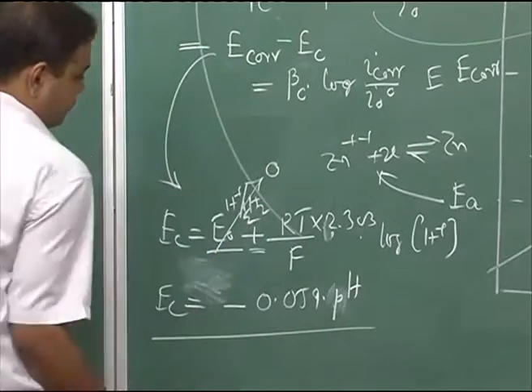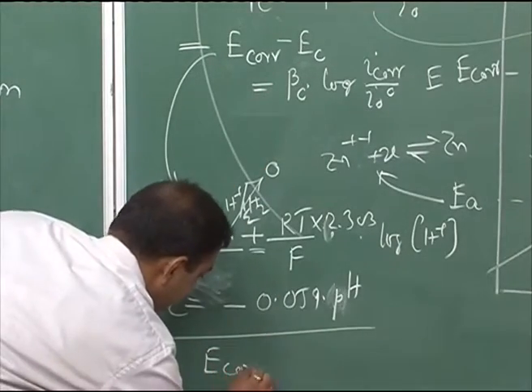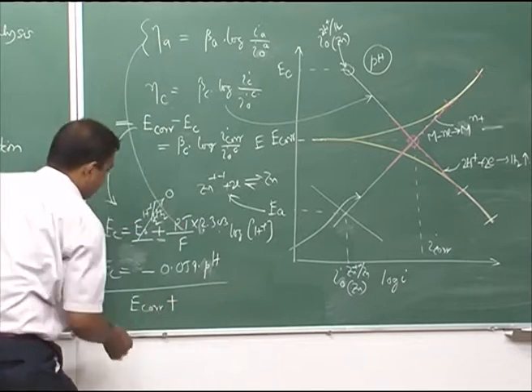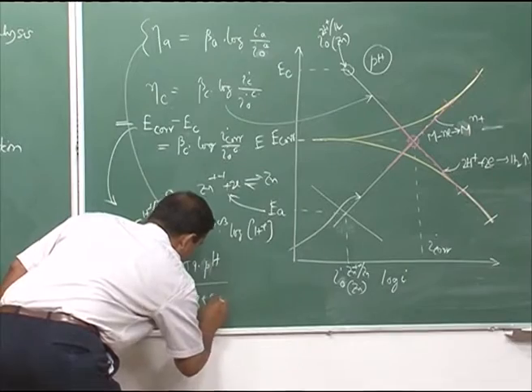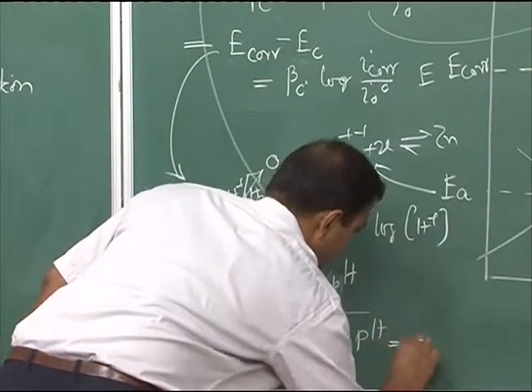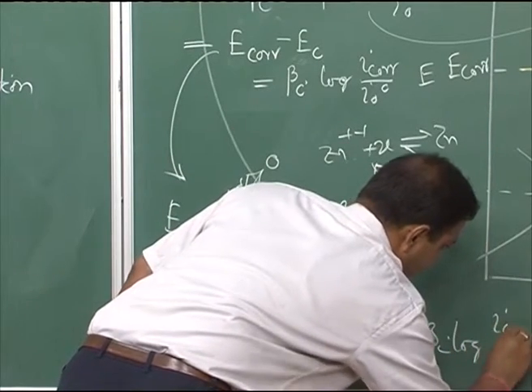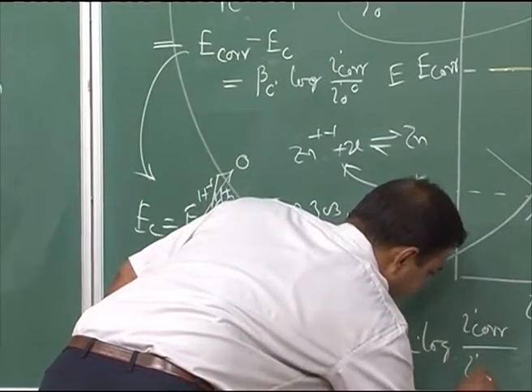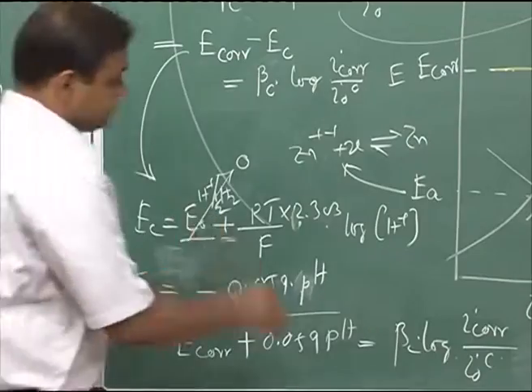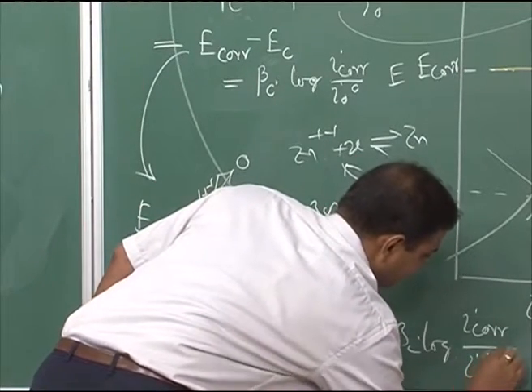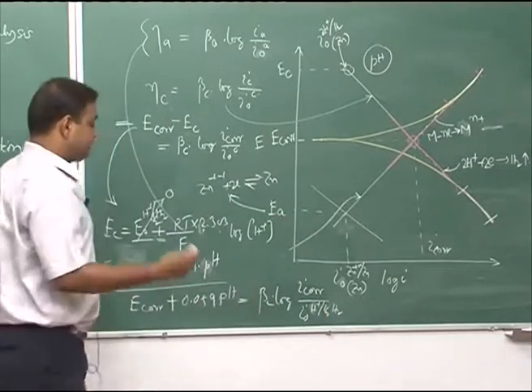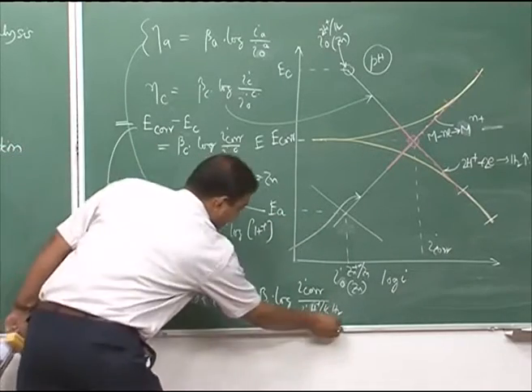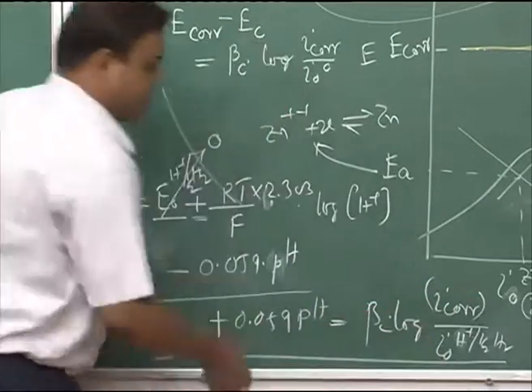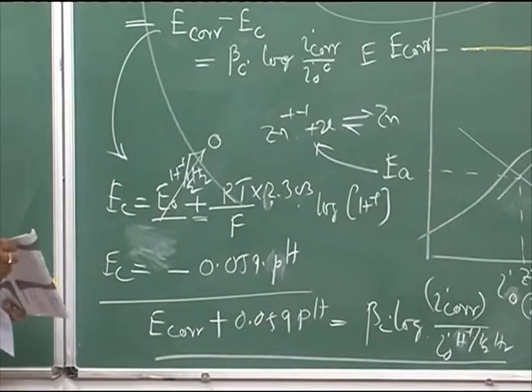We put this here, so the final equation would become Ecor minus, which would become plus 0.059 pH, would be equal to beta c log of I cor divided by I0c, where c in this case is actually H+, half H2, or 2H+ plus H2. So, this is the equation. From this we can find out what is I cor, and if we know I cor, we can find out what is the corrosion rate of that metal in that particular solution.